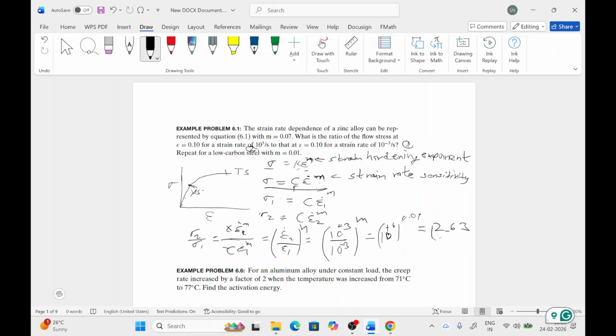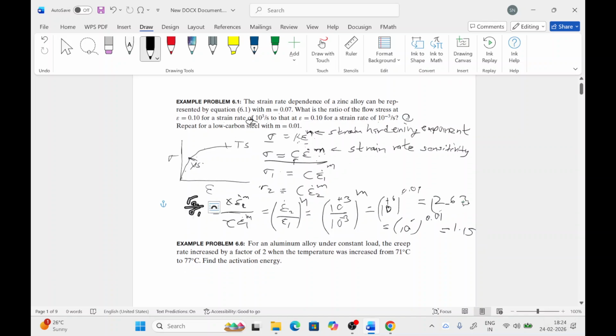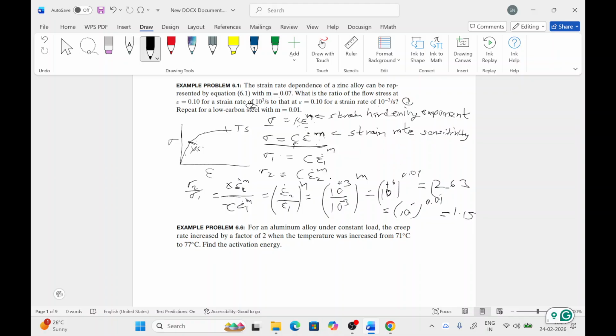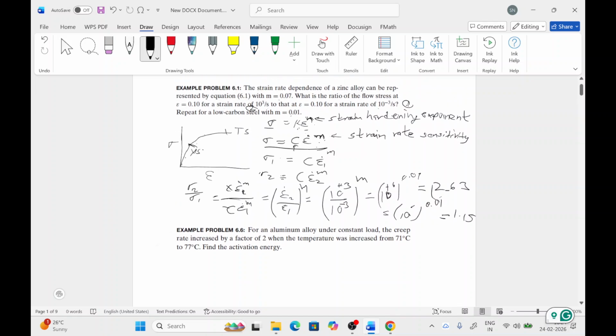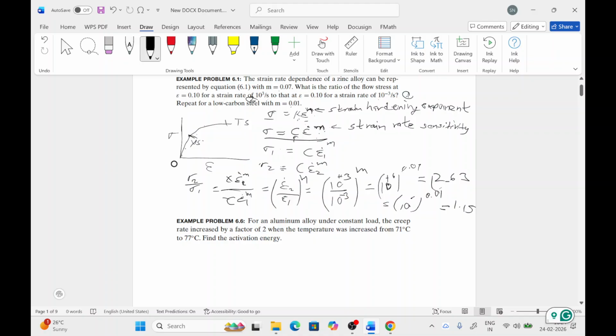And if we want to calculate this for steel, it will be 10 raised to power 6, with m as 0.01. So that will be 1.15. One more thing, the value of m also shows material behavior. If a material has a lower m value compared to another material, here we have m 0.07 for zinc and m 0.01 for the low carbon steel. So the strain rate sensitivity of steel is less compared to zinc. So the response to changing strain rate is much higher in the zinc alloy as compared to the low carbon steel.